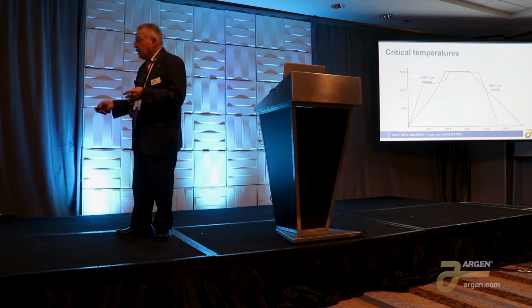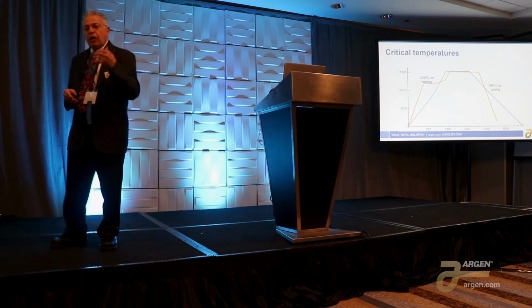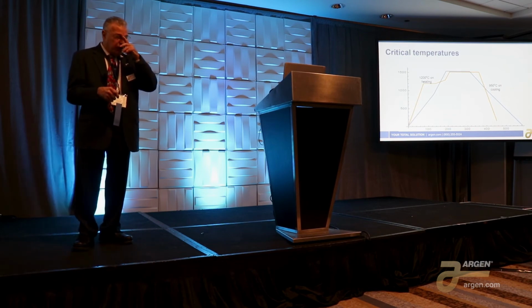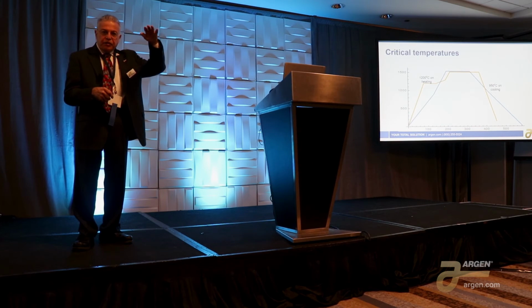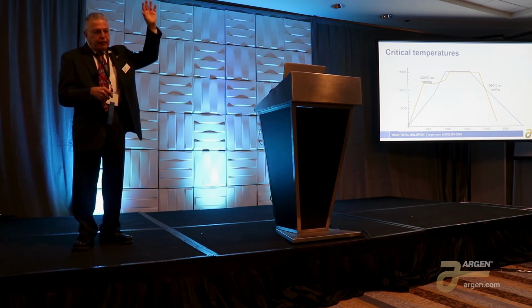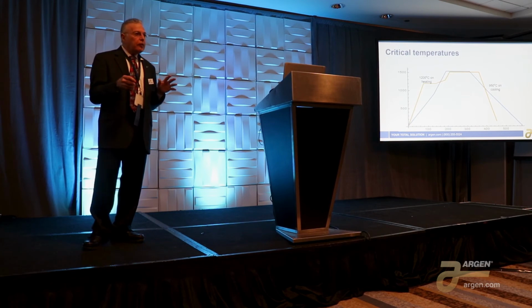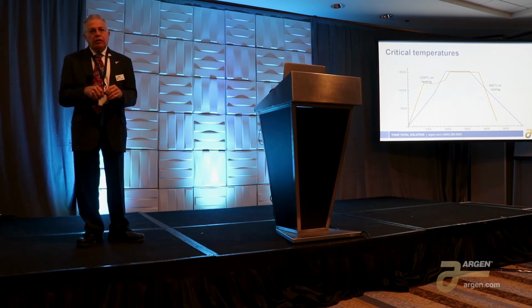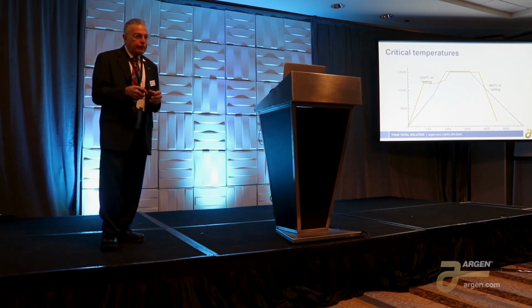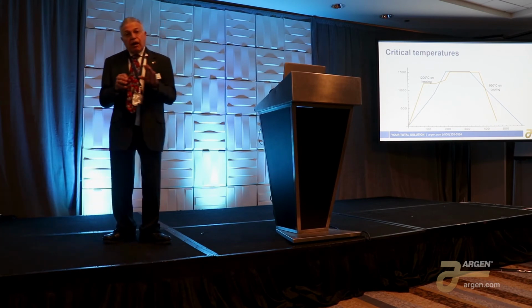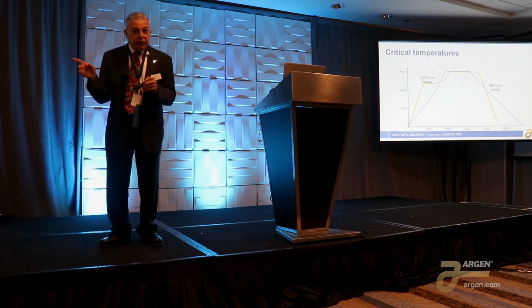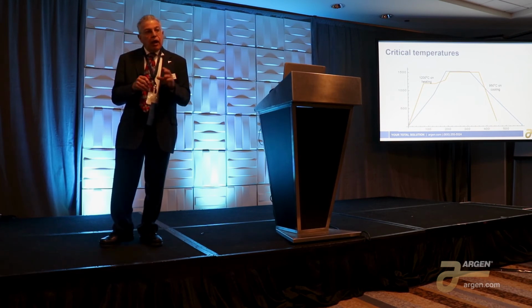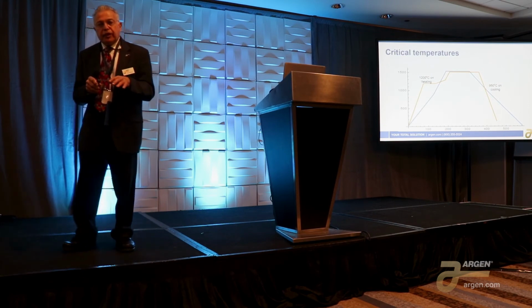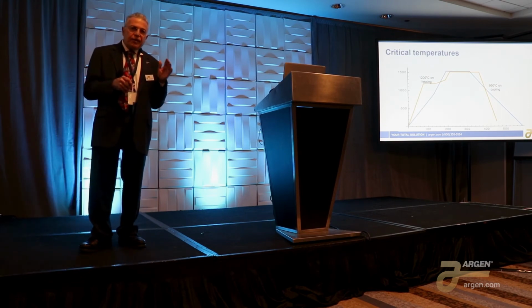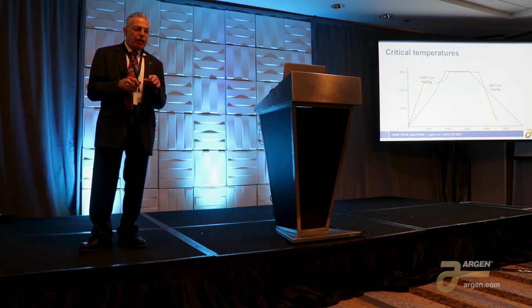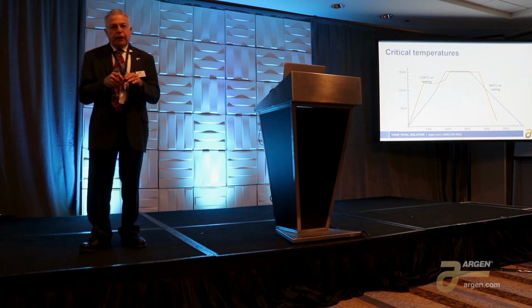Also, the original zirconia, the ultra type zirconia, the high strength materials, it didn't matter very much where you sintered them. You could sinter them anywhere between 1450 and 1550, no problem. It still developed the strength, and you weren't interested in translucency, everything was white. So that was good. Then when we went to the high translucent material, the 5Y material, the 5.5% yttria material, a lot of people found that the sintering temperature was like 1550, but if I went to 1570, it looked a little better.